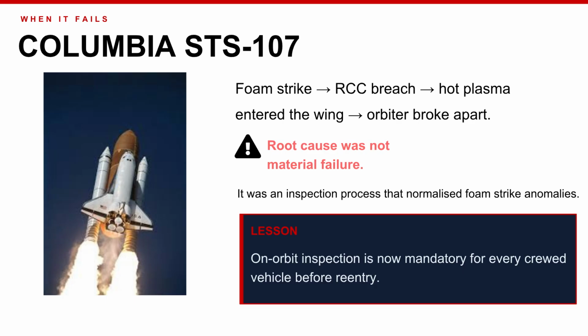On STS-107, Columbia, a piece of foam insulation from the external tank struck the leading edge of the left wing during ascent. The impact damaged the reinforced carbon-carbon panels, a different, even higher temperature material used at the wing leading edges. On re-entry February 1, 2003, hot plasma entered the breach. The wing failed. The orbiter broke apart. The root cause was not material failure. It was a maintenance and inspection process that normalized anomalous foam strikes.